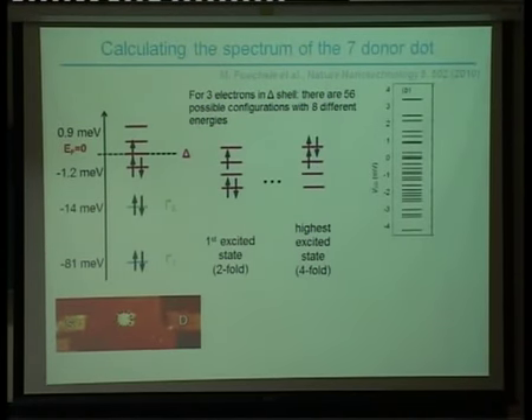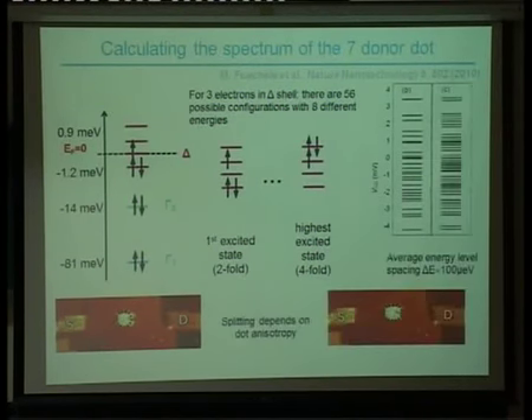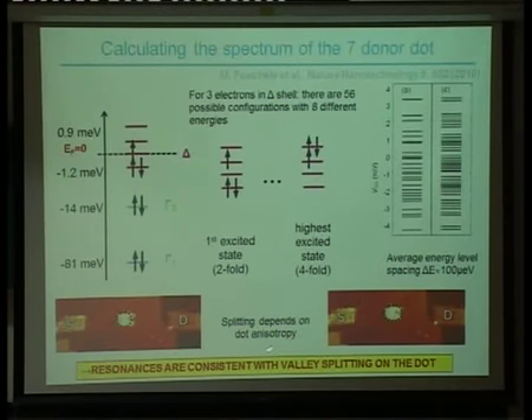what the energy level separation would be for these very strongly confined dots, you can see that we're now starting to get towards this 100 microeV energy level spacing. And indeed, if you take into account the anisotropy of the physical size of the dot, the average energy level spacing is about 100 microeV. So the critical point to take away is that when you strongly confine things in both the vertical and lateral dimensions to create these very small quantum dot architectures, you have to take into account the valley splitting. So valleys are very important in silicon.